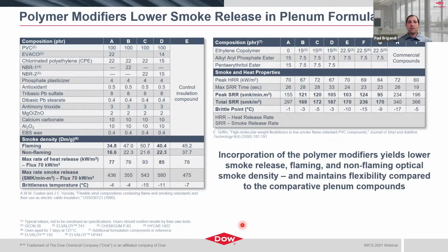So if we take it a step further, I wanted to show a couple of examples of polymer modifiers in plenum-specific applications or plenum-specific formulations. These are both from the literature. In the first example, we have Coker, who worked on a composition comparing the ethylene copolymer modifiers to chlorinated polyethylene, as well as nitrile butadiene rubbers as plasticizer components to the PVC. Again, more of a traditional plenum type formulation as far as additives go.